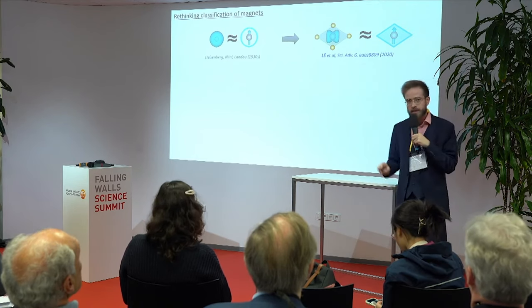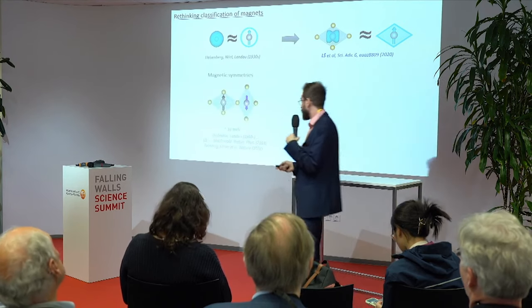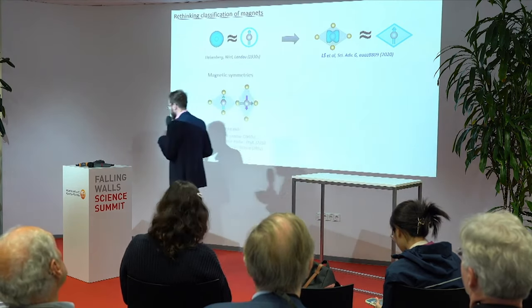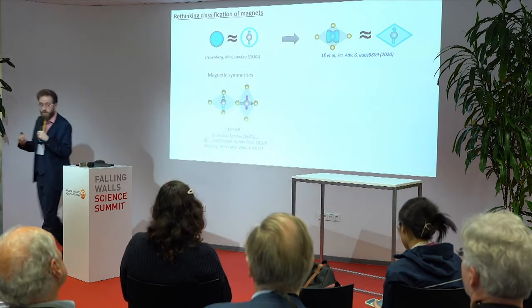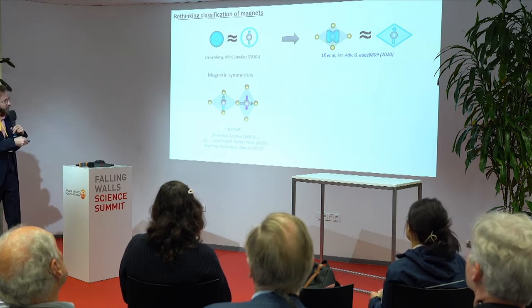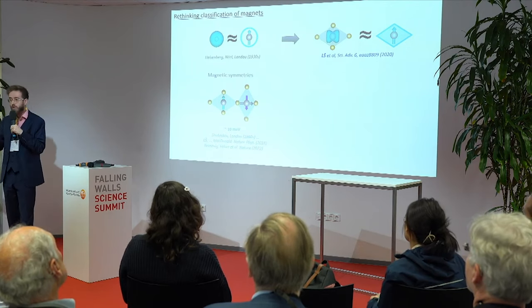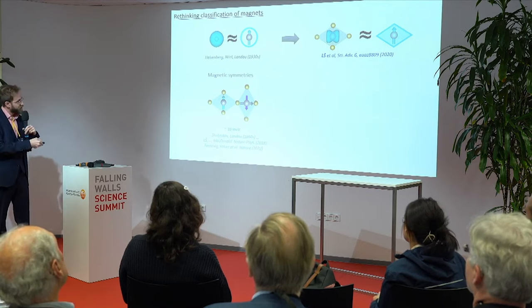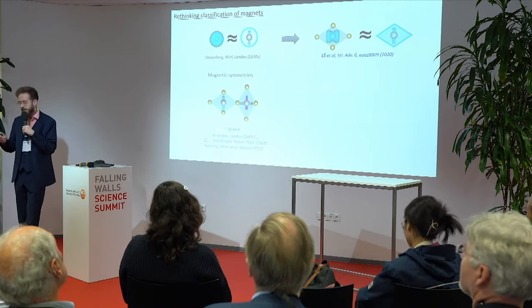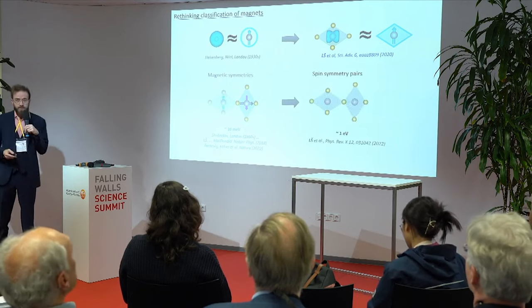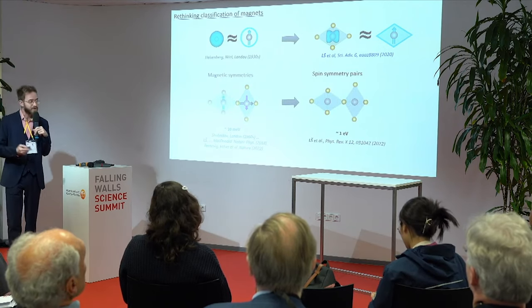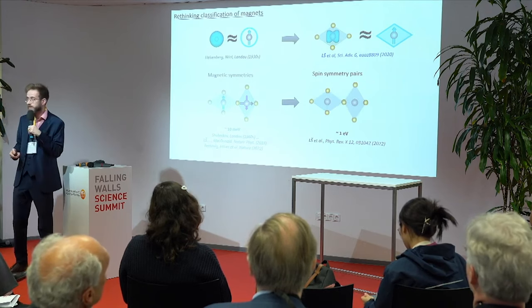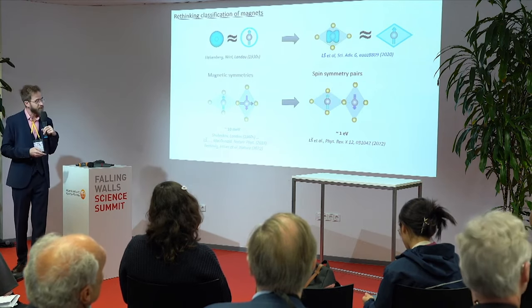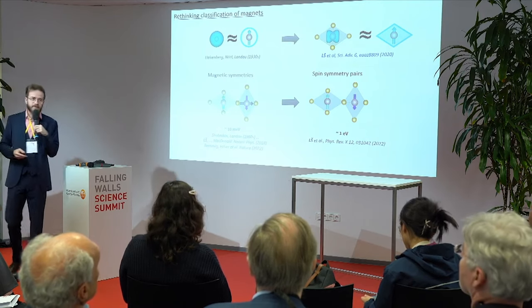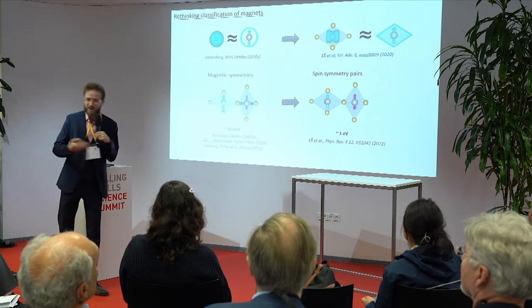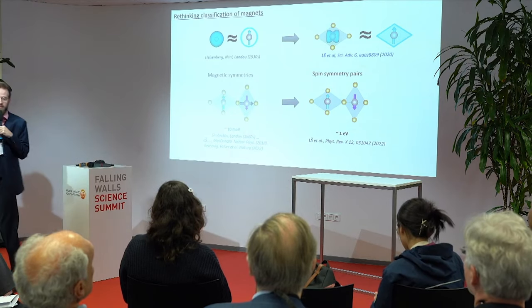which can be understood by this picture of the diamond. The second important aspect is that usually in magnetism, we are thinking about symmetries acting simultaneously on the atoms and on the spins. So for instance, in this example, you have seen that when I rotate by 90 degrees, I need to rotate both degrees of freedom. So I end up with an operation which is not a symmetry of this crystal. However, I can formulate something more general. I can formulate pairs of operations, and then I can rotate by 90 degrees in the crystallographic space, combined with 180 degrees in the spin space. And such symmetry operations are more general, and they now allow me to find all possible magnets.